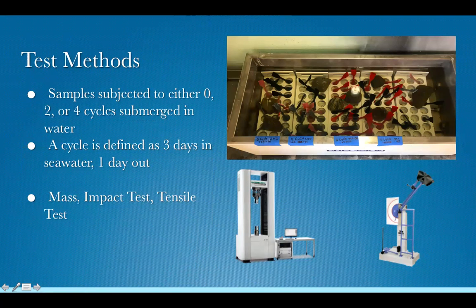Submerged samples spent 0, 2, or 4 cycles in seawater, with each cycle consisting of 3 days in the water and 1 day out. Tensile and impact tests were then carried out to ascertain how physical properties changed post-immersion. Tensile tests involve subjecting samples to an extended pull to get information on tensile strength, and impact testing involves swinging a pendulum hammer into the sample to see the energy absorbed before fracture.